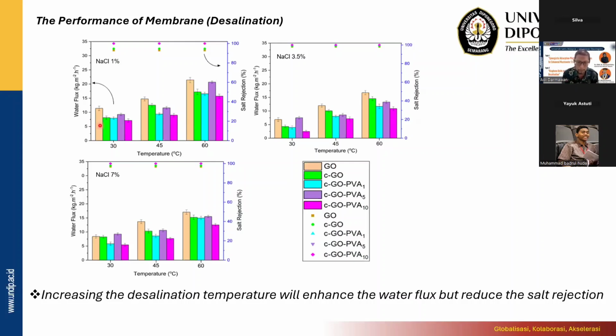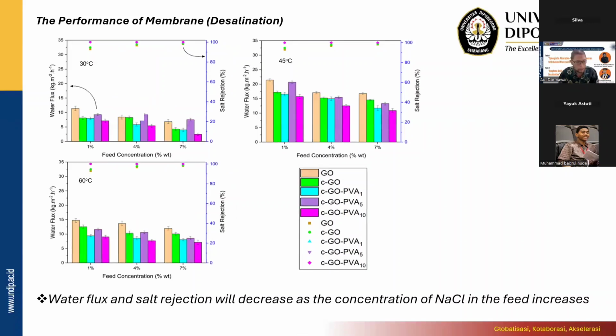So actually this membrane can reduce the energy, because if we desalinate salt water we need to boil the water up to 100 degrees. Too much energy, because the specific heat capacity of water is actually very high. So we can reduce the energy consumption by using the membrane. Okay, this is the first publication about this one. Okay.